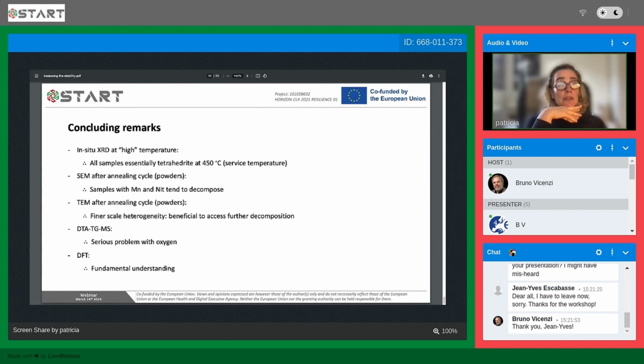So although in the literature people cite manganese and nickel as having a good thermoelectric behavior, people never really show 2 things. One is what happens when you cycle many times, in terms of the ZT behavior. And most of all, I've never seen any studies where people show you the samples after a long time annealing or after cycling many times.